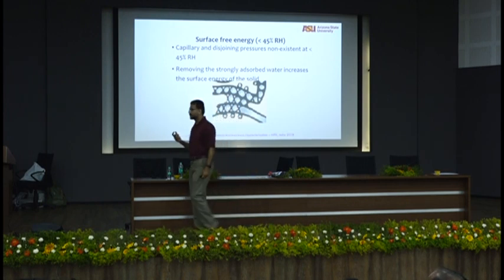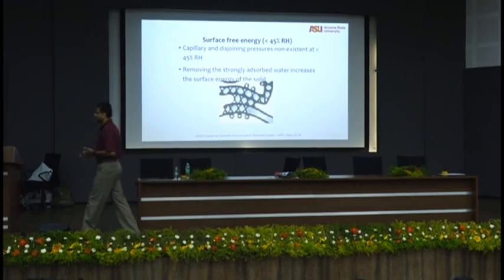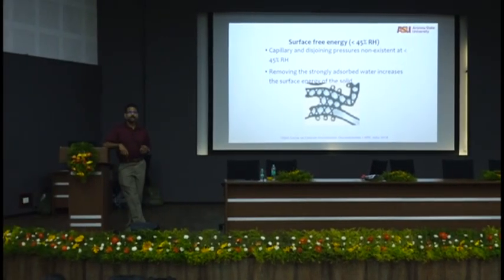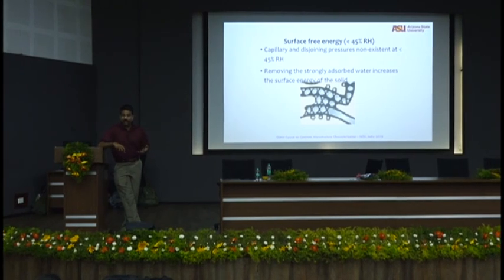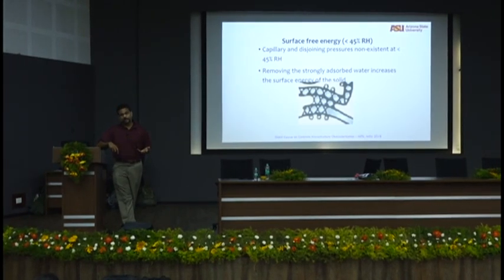The consequence is that you will have cracking, very fine microcracks. You will have extremely fine microcracks because this is happening at really small pores. So the concrete will be extremely microcracked because of this. Won't be visible, no, these are at a very small level. But under load, under constant fatigue, all these cracks will grow.